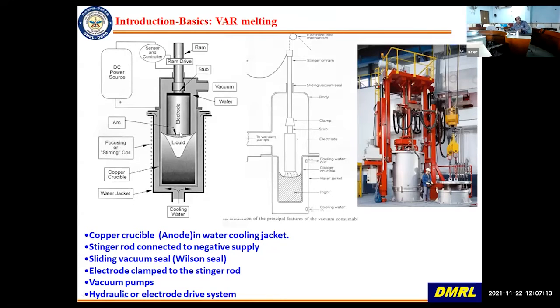And so you arc between the electrode and the bottom of the crucible and start the melting, and you keep pushing the electrode down. So this is what you have, and the vacuum is applied through vacuum pumps. So this is again a schematic. You have this vacuum pump, and then you have this copper crucible in which it melts and solidifies part by part. Okay. So this is a picture of an industrial scale furnace, which is, most of it is underground.